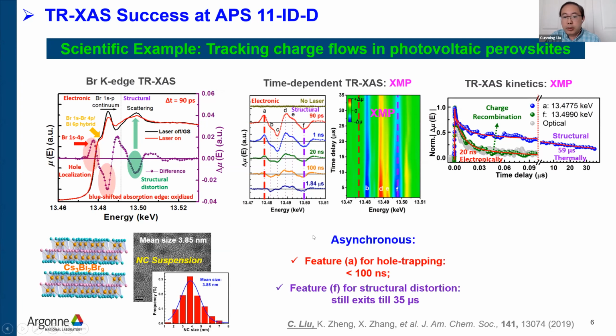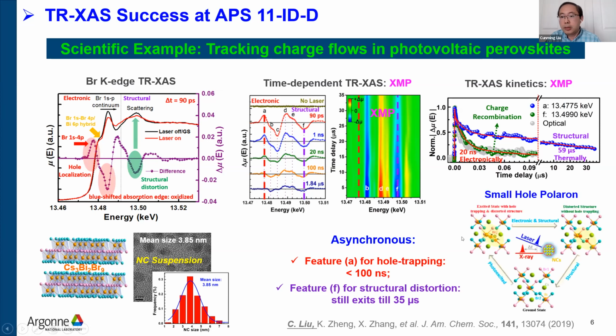So here we found that the electronic and structural relaxations in the perovskite nanocrystal are asynchronous. Since we found that the hole is localized at the bromine site with the local structure distortion, we propose a small polaron mechanism to interpret what we have observed.